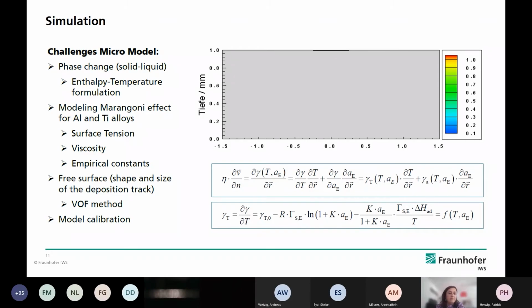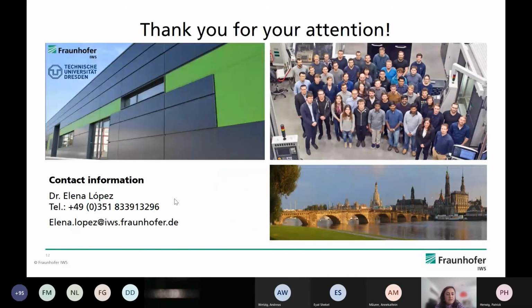So we will study the surface tension, viscosity and empirical constants, and then the free surface issue will also be taken into consideration. I mentioned we can modify also the shape and the size of the deposition track, and we'll focus on this also for the feedback from the simulation. And finally, use all of these facts for the model calibration. So this is from my side.